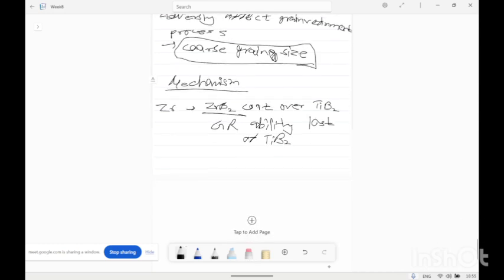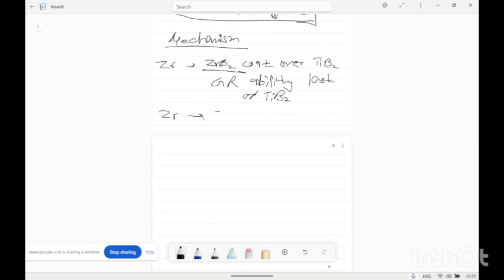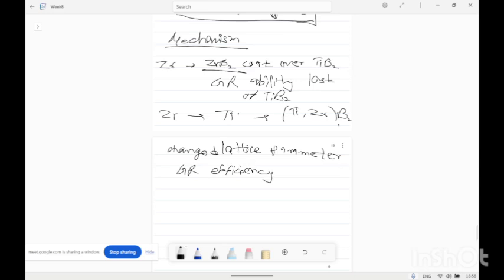Or if zirconium substitutes for titanium and forms the titanium zirconium boride, it changes the lattice parameter. So this boride has the changed lattice parameter that will have a high misfit with the aluminum atoms and decrease the grain refinement efficiency. So the grain refinement efficiency is altered because of the formation of titanium zirconium boride.